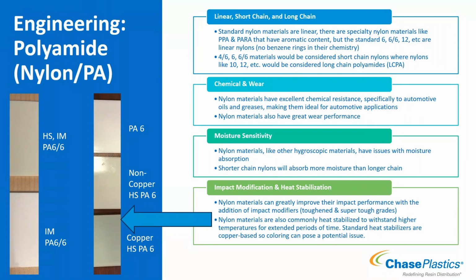Nylon also has really great wear performance. In terms of lower speeds and velocities, it's not quite as good as acetal on metal, but it is way better than acetal if nylon is wearing on itself. So resin on resin wear, nylon takes the win there compared to acetal materials.